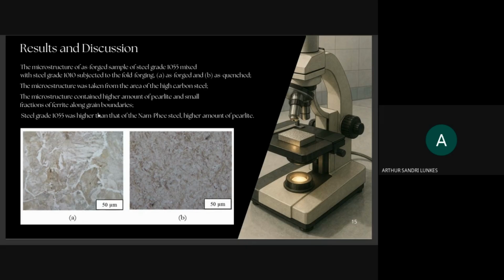This picture here is the microstructure of 1055 steel and 1010 steel. This one here is only forged, and this one here is quenched. Okay. The microstructure was taken from the middle area of the high carbon steel. The microstructure contains a high amount of pearlite and a small fraction of ferrite. Maybe because the high carbon steel has more carbon, so we have more pearlite in consequence. So the microstructure contains a high amount of pearlite and a small fraction of ferrite along the grain boundaries, like I talked before. The steel grade 1055 has a higher amount of pearlite than the Nam Phe steel. He said that this steel here has a higher percent of carbon than the Nam Phe steel.